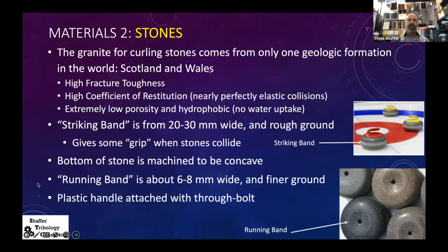But this granite is so nice, and other granite just doesn't work for curling because it's got a very high fracture toughness. It's got a high coefficient of restitution, so you have nearly perfectly elastic collisions when the stones strike one another. It has extremely low porosity, and it's hydrophobic, so there's no water uptake. So it's not going to have this freeze-thaw cycle, which brings mountains down to grains of sand eventually. Those are the really good properties of this type of granite.